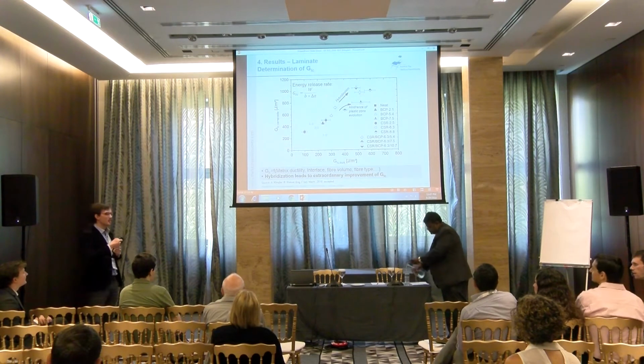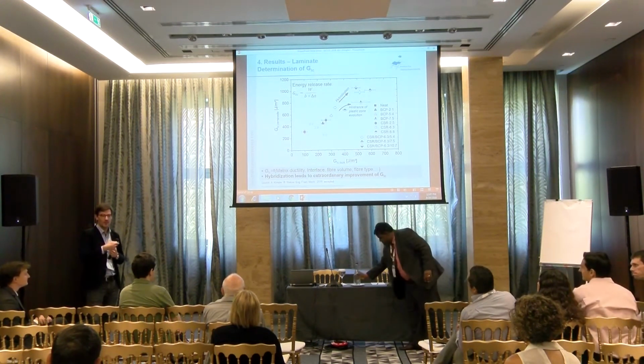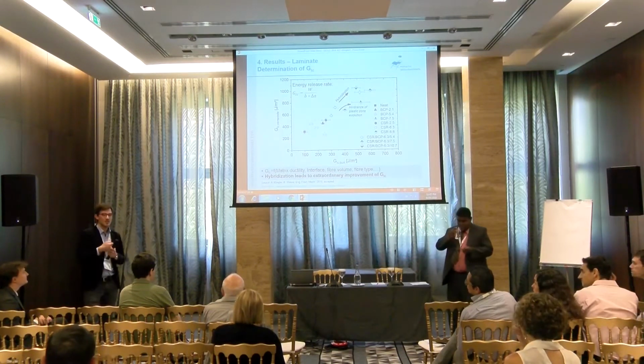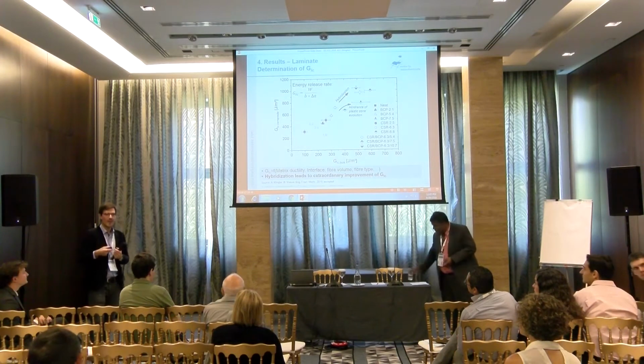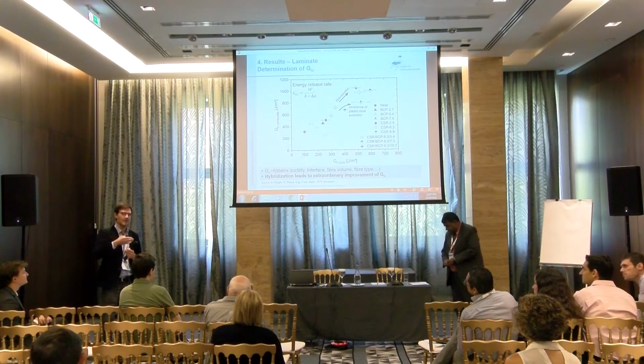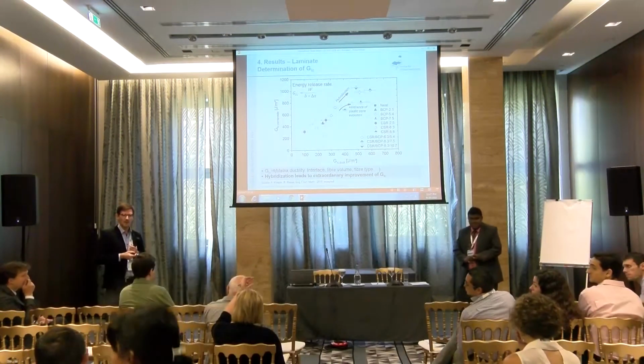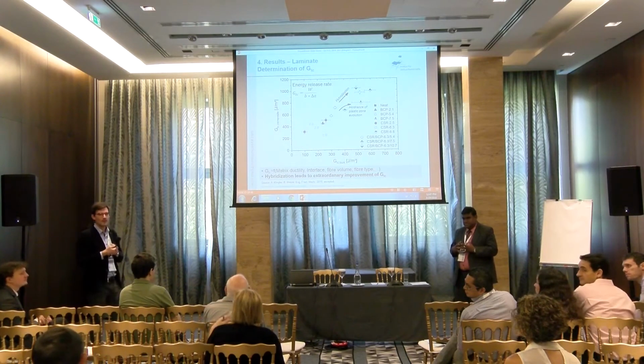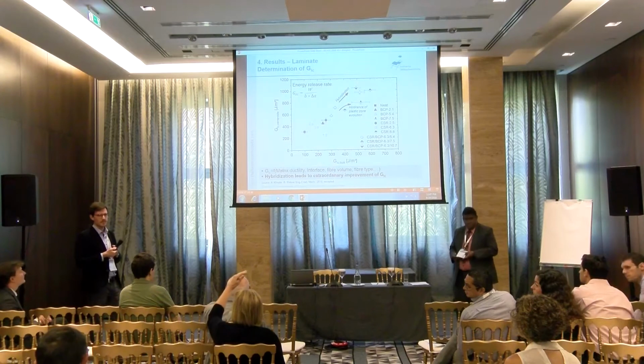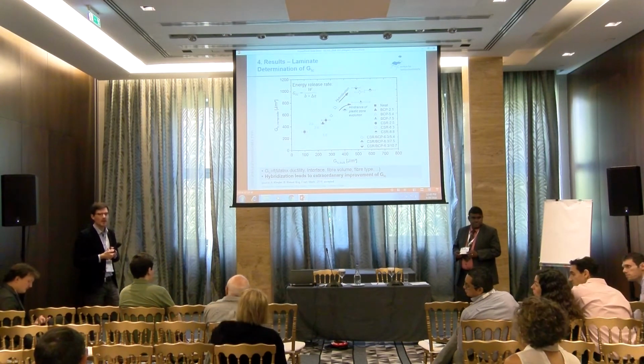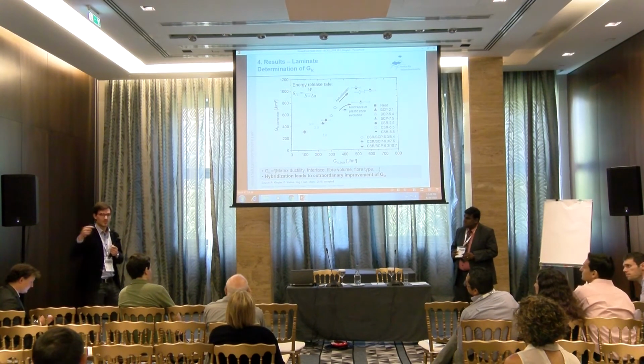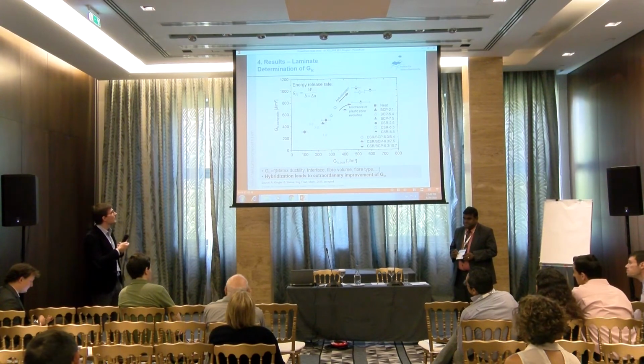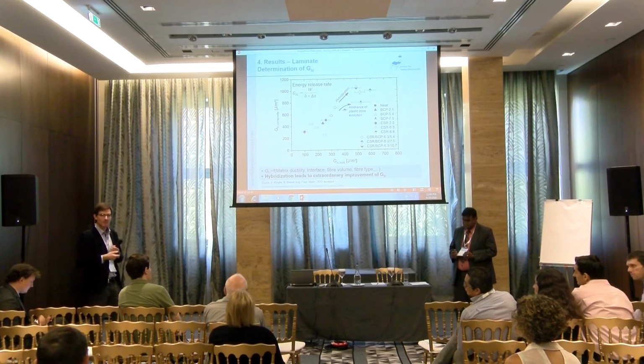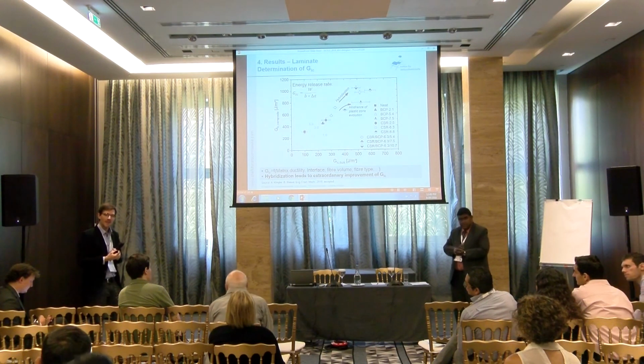In the end, it does not really matter because you get an average value of your crack propagation value, right? Is this an initiation value? No, this is not an initiation value, this is a propagation value. Initiation values were obtained, but they are not presented. When you get your force displacement curve, you can also take a look at where the curve leaves its linearity. You have a GR curve, so you have an initiation value, and then you have an increase in the R curve, and then you usually settle down. Exactly. So W is the energy below your force displacement curve, and you relate it to your sample size and to the crack propagation delta A. So it gives you more or less the same values as the ASTM and ISO standards.